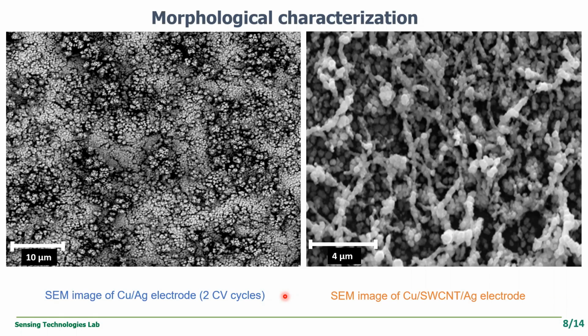So this is the morphological characterization, and here in this slide, the left side, the SEM images are from the copper silver sensor where 2 CV cycles were used. It is observable that the copper electrodeposition was not uniform all over the working electrode, and some silver flecks are also visible. On the other hand, from the right side of this SEM image, it can be seen that each single wall carbon nanotube is uniformly covered with globular shaped copper nanoclusters. The average diameter of the copper nanoclusters is from 200 to 500 nanometer, which perfectly matched with the recent literature. Also from the image, it is visible that the surface area increased.